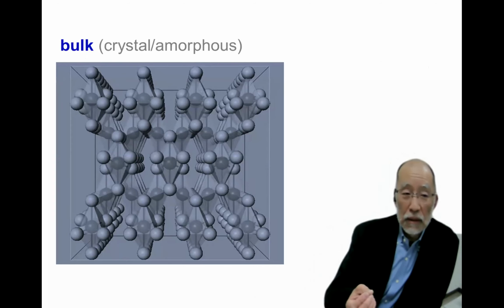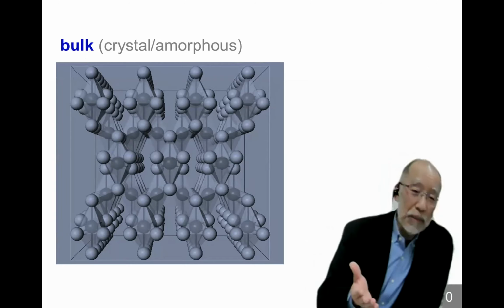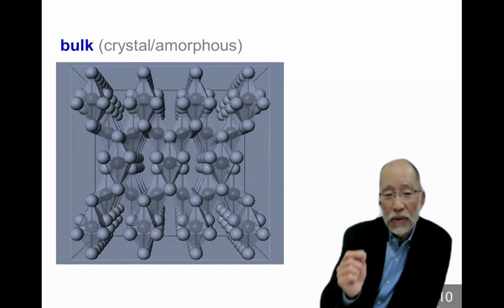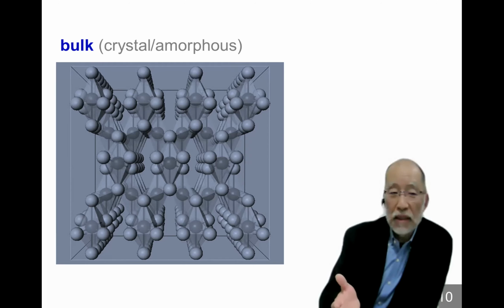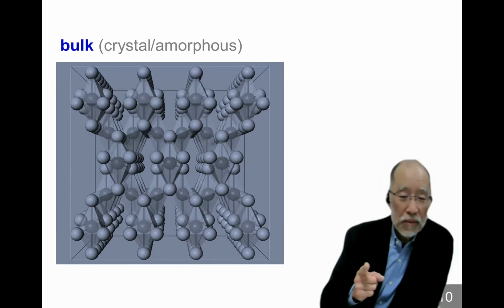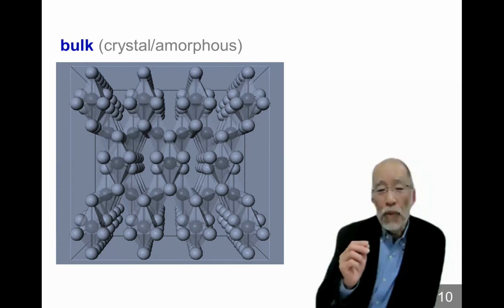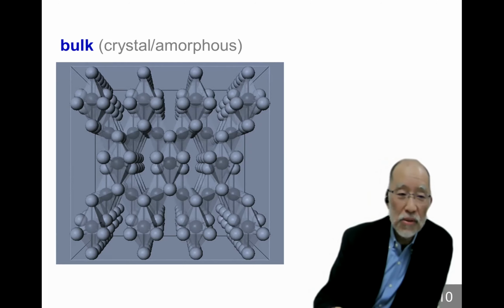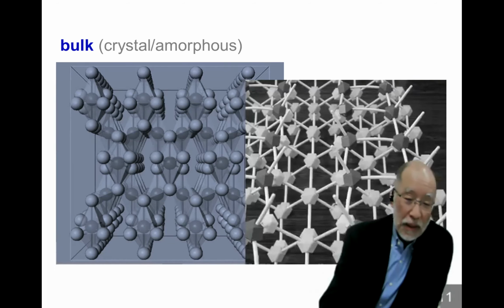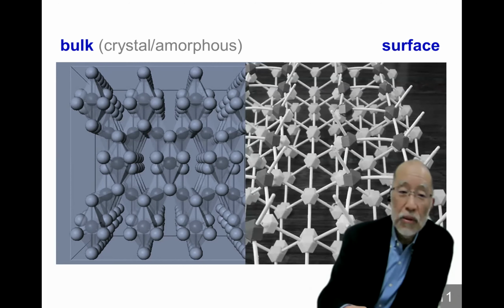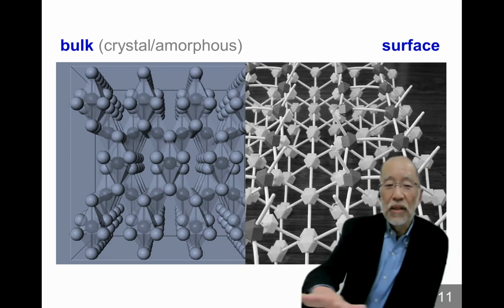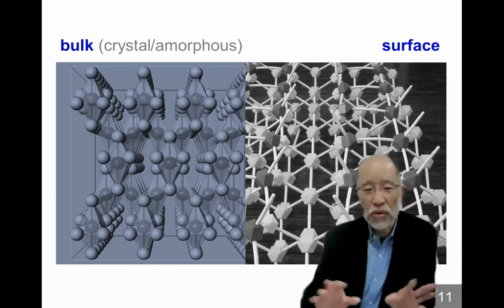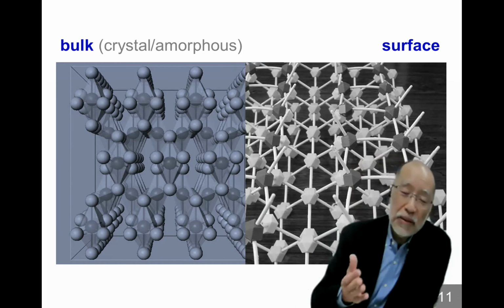As IUPAC recommendation said, it is so much difficult to determine the structure because at least the solid material has bulk structure. And probably you think it is not so difficult because the XRD shows the crystalline structure as a bulk structure. But that is based on the neglection of amorphous phase. And we neglect the presence and how much amount of amorphous phases are there. We neglect it. And solid material, of course, has surfaces that is completely different from bulk. And it is a bit difficult or rather difficult to describe the surface structure. And of course, there is some distribution of different type of surface structure. So that is so much difficult.